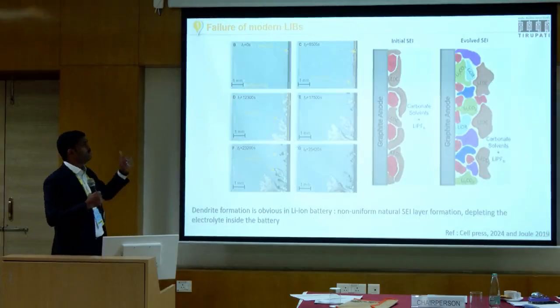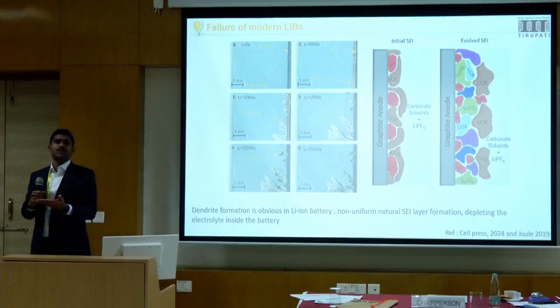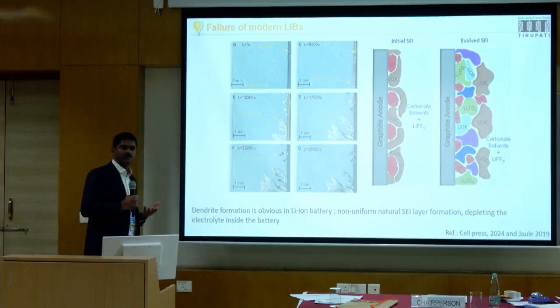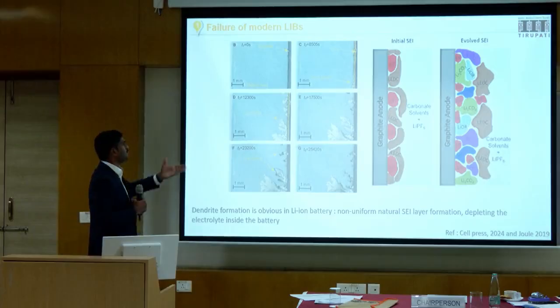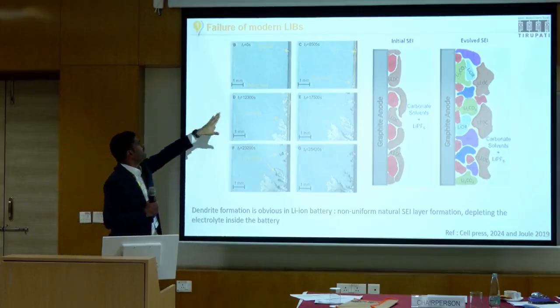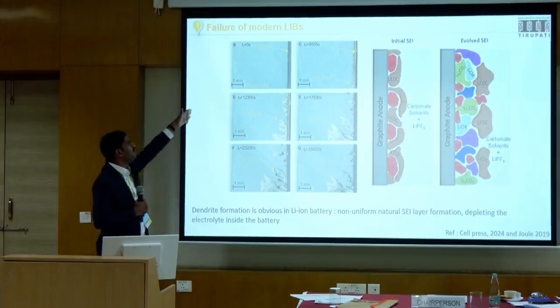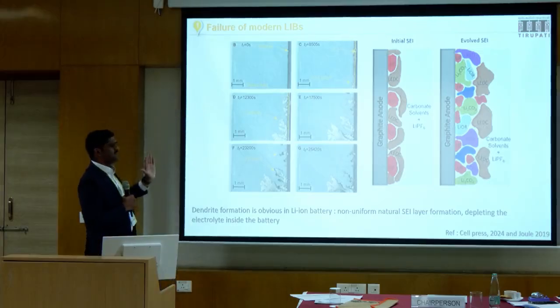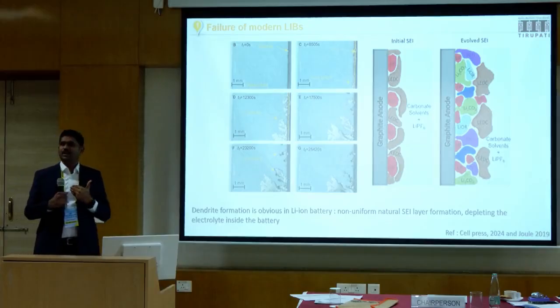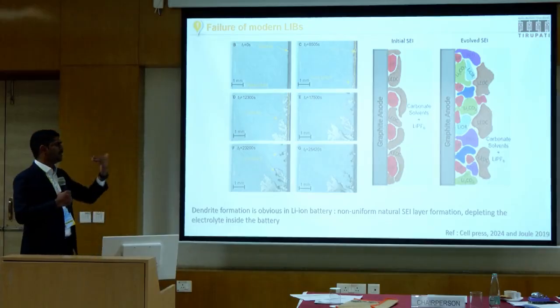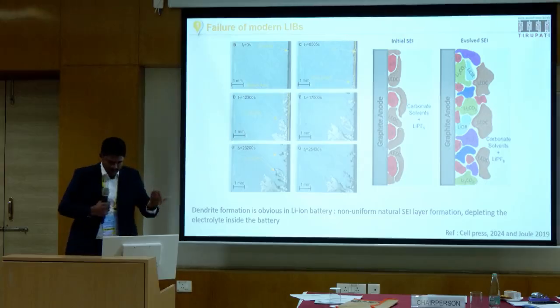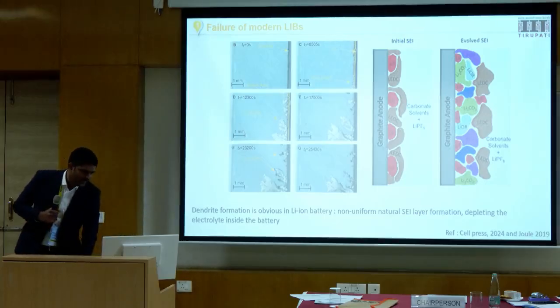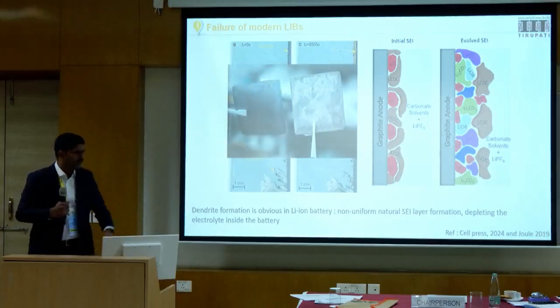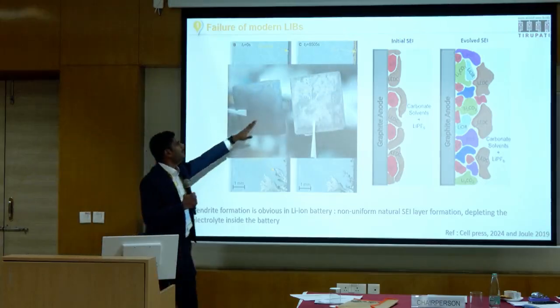And looking into the failure mechanism in the modern rechargeable battery, what we have in our mobile phones or laptops is obviously a graphite anode and a lithium cobalt oxide cathode. Even in this case, rather than lithium ions moving between the anode and cathode, the ions started to deposit over the anode as lithium metal.